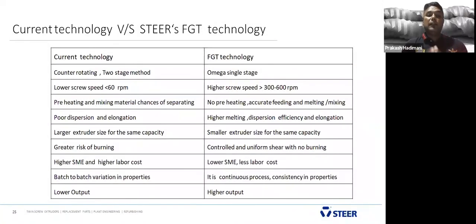I'm just comparing the current technology and our FGT technology. The current technology I'm talking about today is counter rotating, a two-stage process. If you look at WPC and natural fiber, still 80% of the customers in the industry are using single screw or the counter rotating method. What are the drawbacks of the counter rotating method? You cannot go more than 60 RPM; you have to run at the lower RPM. But Omega is a single-stage process, whereas counter rotating is two-stage. You have to mix and then go to the next level. And Omega can be run even at 300 to 600 RPM.